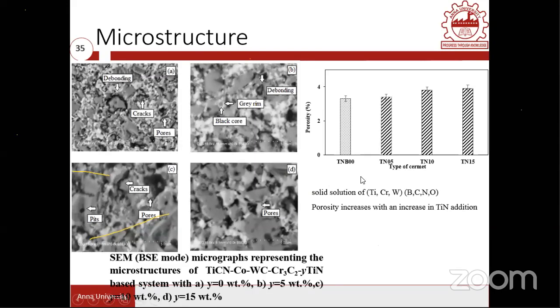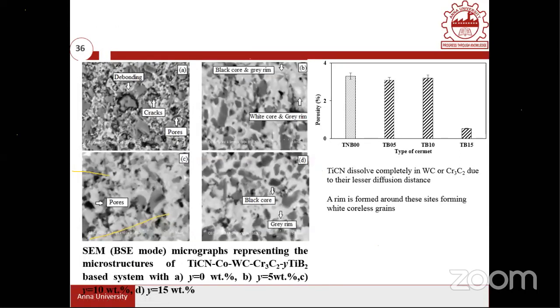Sometimes networked porosity is also good in improving the toughness, but the porosity should not be too much. It should be limited porosity with homogeneous distribution. As a result, probably you will have a good improvement in the toughness value.